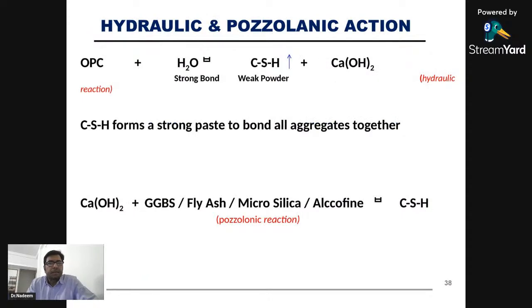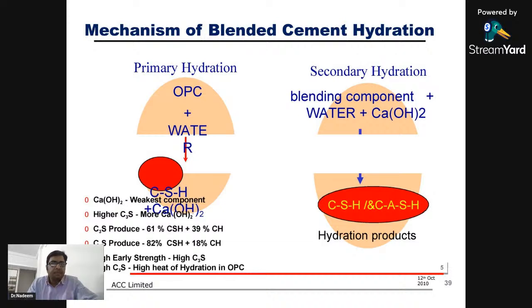So this is a reaction being explained with OPC, water, CSH, and byproduct in the form of calcium hydroxide. Again, CSH being formed, which is a very strong paste which binds all the aggregates together. But again, once you have calcium hydroxide, that is to be utilized by way of supplementary cementitious material, either GGBS, fly ash, microsilica, ultrafine GGBS, or alcofine, and again it forms the CSH gel. So this is a primary hydration, OPC, water, and this is a secondary reaction. So whatever the calcium hydroxide, again it reacts with water and pozzolanic material, silicates, and again it gives the CSH or CASH, calcium aluminum silicate hydrate products. Again, this is, you can say, a cementitious material which imparts the strength to the structure.